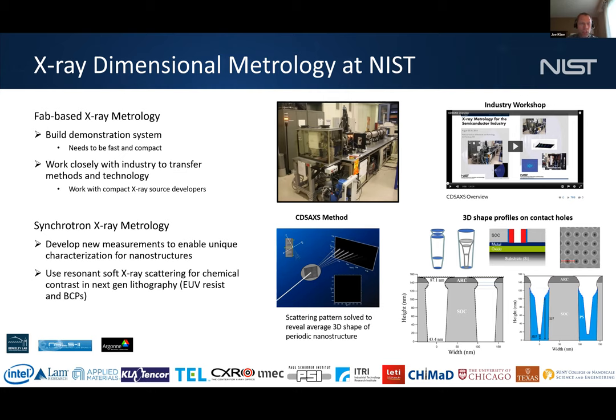And then kind of the other half of the project is the synchrotron X-ray metrology. And so here, we're oftentimes trying to develop some sort of new measurement with unique characterization capabilities for nanostructures. And so it may or may not be something that can eventually transition to the fab. It all sort of depends. And one of the key areas in there that we've been developing, that I'll talk about quite a bit today, is using resonant soft X-rays. So we're doing essentially similar measurements to the CD-SAXS method, but instead of hard X-rays going through a whole wafer, we're using soft X-rays so we can get the chemical contrast, particularly in a lot of lithography materials. And you can see a number of the different collaborators that we have on various projects over the last couple